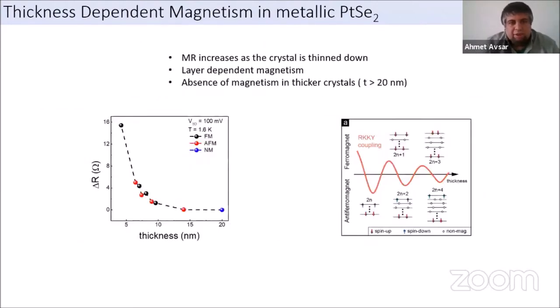So if we combine all the measurements that we were doing, we got indeed an interesting observation. You could already see these black dots are ferromagnetic ordering, and then the red ones are antiferromagnetic ordering. And what we do see is they're alternating, okay, device to device, and it looks like it's depending on the thickness. And the magnitude is decreasing as you increase the thickness, and indeed above 20 nanometer, we never managed to probe any magnetism, even at the lowest temperature. And this looks very similar to the simple picture we had.